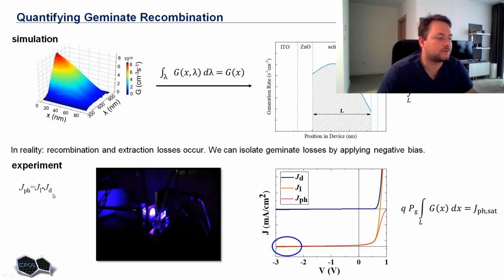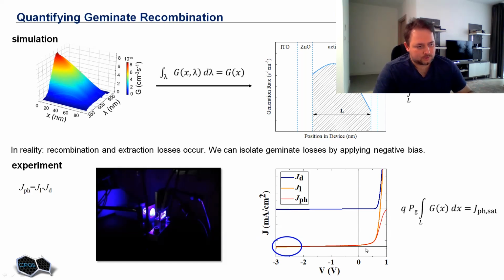Then in real devices, we shine monochromatic light with different wavelengths on our devices. Under this monochromatic illumination, we first measure the dark JV curve without illumination. Then we measure the light JV curve, and the difference between light and dark gives us the photocurrent. So this is this curve. At some reverse bias, close to -3 volts, the internal electric field is so strong that it very efficiently separates already split excitons into free charge carriers, electrons and holes, and doesn't allow them to recombine non-geminately.